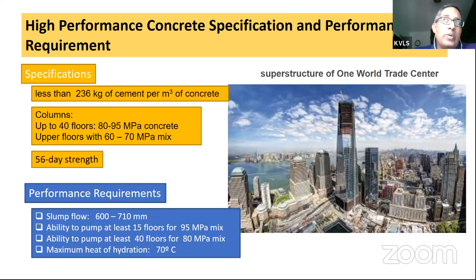Now, that of course requires very careful thought of mix design, where supplementary cementitious materials have to be used, slag and fly ash. Optimization has to be done. Careful mix design has to be done in terms of packing of aggregate and cement in order to achieve these specifications. In addition, there were performance requirements that were put in place.